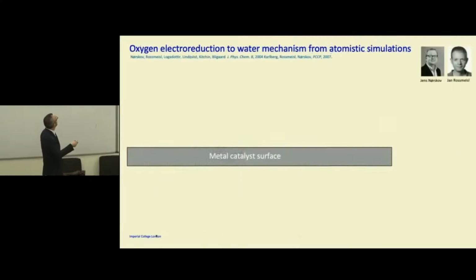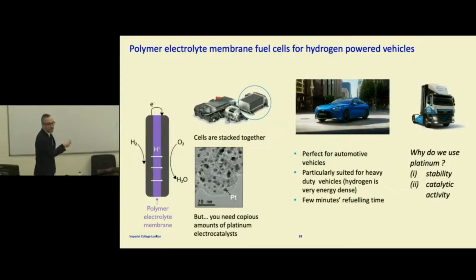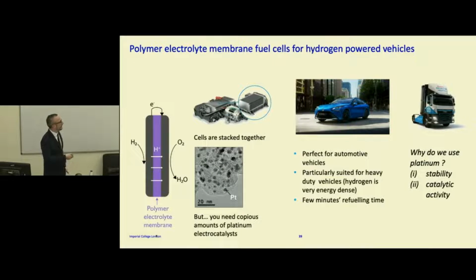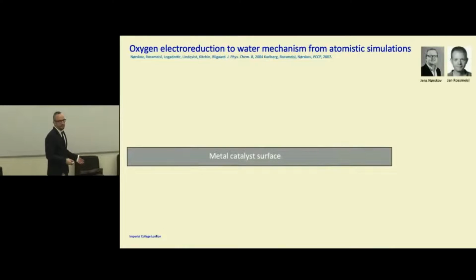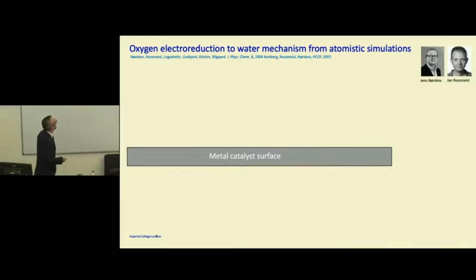Well, partially, it's because you're working with a very acidic electrolyte. It means every metal dissolves except for platinum and gold. And also because you need high catalytic activity or reaction rates. So luckily, in the group where I was, they were doing a lot of theoretical calculations to try and understand electrochemical systems. And in electrochemistry, usually what we do is we measure current as a function of potential, and we try and conjecture what's going on. And it's very rough because it's very difficult to understand this complicated surface.